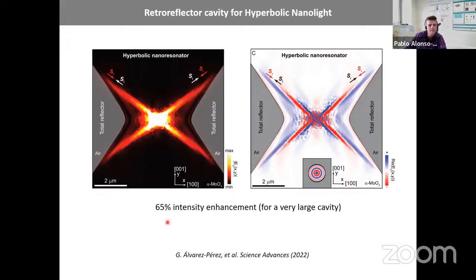And we calculated the intensity enhancement at the center. It was 65%, but this was for a very large cavity, like 4 microns, because we wanted to see this effect in this simulation. So you can reduce this size to really small volumes. Actually, you can make it infinitely small volume because you have really, really large K along this direction, because it's the asymptote of the hyperbola. So you can confine light really at tiny spots. Okay.